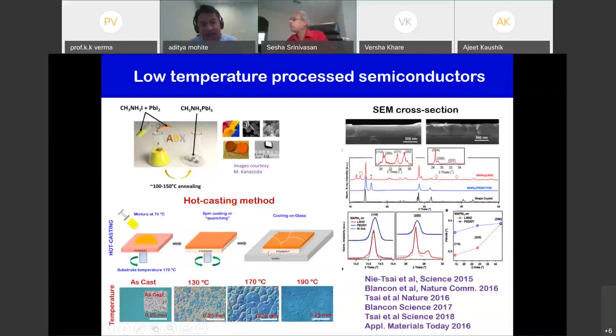And then when you end, what you get is something that looks like this. So below, I'm showing you optical images. The first one is, of course, electron microscopy. You can see the as-cast film has grains which are really small. But as you increase your casting or your substrate temperature, we saw the formation of grains which continued to grow larger and larger. And so we were able to get grains of the order of about a millimeter in size.